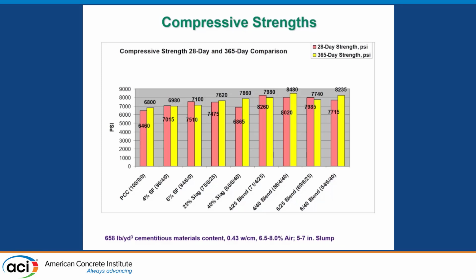So here's what happened in the compressive strength. As we can see over the course of time, the Portland cement is about 6,800 psi, but as we start making these a better ternary blend with the same cementitious contents, at a blend of basically 4% silica fume with 40% slag cement, we're at almost 8,500 psi. And then again, 7,900 when we look at these other blends. So where am I really getting the bang for the buck? And here's where we have to start looking economically.